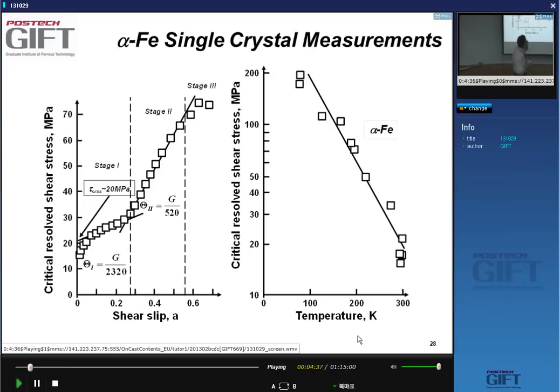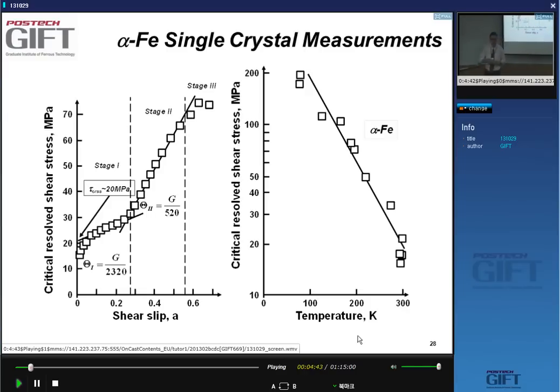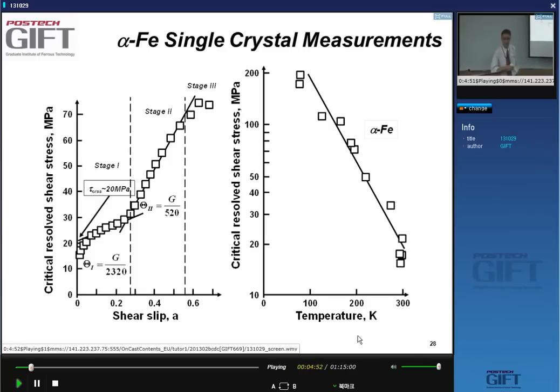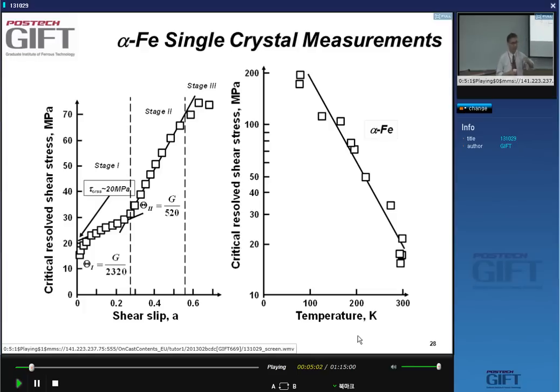If we look at the temperature dependence of this critical shear stress, at around room temperature we're around 20 megapascal. As we decrease the temperature, you can see a very strong increase. From the data, if you extended the straight line to 0 K, you wouldn't be far from 400 megapascal. So is it correct that the dislocation actually jumps at low temperature from one Peierls valley to the other? For alpha iron and ferritic steels, it's more complex — that's not what's happening.